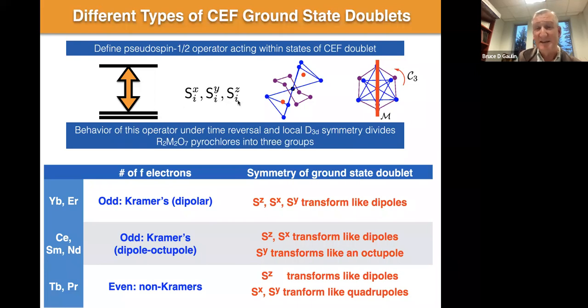And we can look and see how those components behave under the symmetry operations of the point group symmetry at the rare earth site in this structure, and time reversal symmetry. It turns out that within this structure, the symmetry operations that are relevant include a threefold rotation symmetry as you rotate around the Z direction.